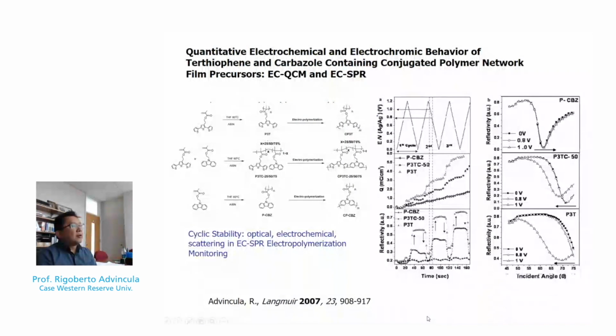Now, a lot of things we developed later on involve what we call in situ measurements that combine electrochemistry and SPR. As shown here, we have the electrochemical parameters on the deposition of what I call a precursor polythiophene derived from this terthiophene oligomer that we attach to a polymethyl methacrylate backbone. And what happens is that as we deposit them by cyclic voltammetry up to, let's say, the 4th cycle here as shown, the amount of charge can be calculated based on the electrochemistry experiment with the various copolymers and compositions